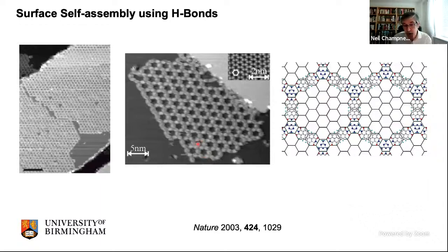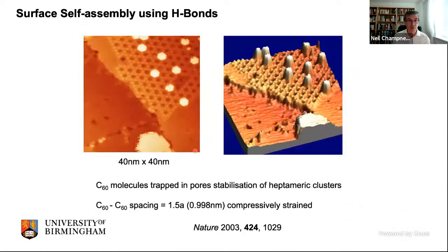There are big holes within here where we have exposed surface underneath. These pores are 2.5 nanometers across, and they are suitable for absorbing C60. We can actually absorb lots of other molecules as well, but C60 was a good starting point. And the C60s essentially roll across the surface and are trapped within these pores.